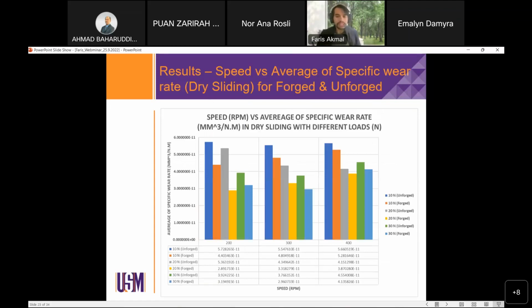Okay, the results. This is the result for dry sliding, speed versus average specific wear rate, for forged and unforged cases. Now, as you can see from here, look at the pattern. As speed and load increase, for both cases, the average specific wear rate decreases, as speed and load increase from 200 rpm to 400 rpm for different loads from 10 newton to 30 newtons. But if you compare forged and unforged, the forged specimen has a lower average specific wear rate than the unforged.